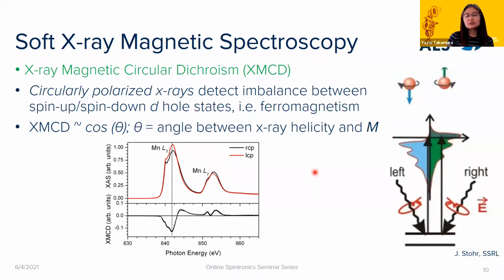And then just as background, to make sure everyone understands the technique that we're using: in general, what I'll be showing is the use of soft X-ray magnetic spectroscopy. I call this the overall umbrella of the technique, and we'll have two different variants of it. The first variant is XMCD, or X-ray magnetic circular dichroism. Out of the two, it's probably the more commonly used technique. With this technique, we're using soft X-rays, in the range of a few hundred to maybe 1,000 electron volts. And these are tuned to the different absorption edges of the elements in the material.